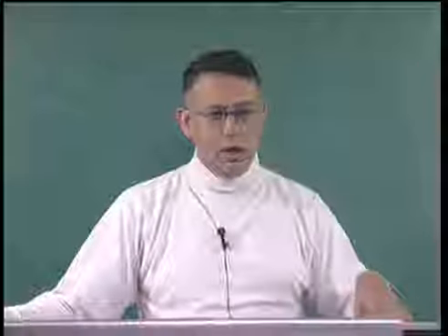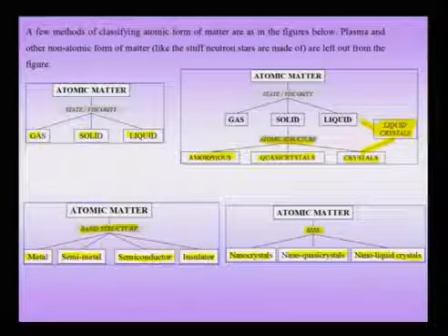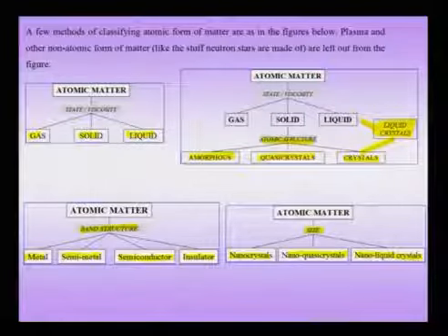This atomic order automatically translates into the kind of properties that each of these phases would show. For instance, we know that a crystal can have defects like dislocations, and therefore they are plastically deformable. You can easily form them at room temperature into various shapes. An amorphous phase, on the other hand, cannot be plastically deformed and would typically fracture. We know that silicate glass at room temperature is very brittle. Of course, if you heat it up to high temperatures, it can flow like a fluid. It will have a low viscosity, and then it can be blown into various shapes, including a glass bottle. Therefore, this atomic structure automatically translates into the properties, and whenever I am using any of these crystalline, quasi-crystalline or amorphous phases, I would worry about their atomic structure, their band structure, and also their size before I engineer a material which can then be put to good use in an engineering application.